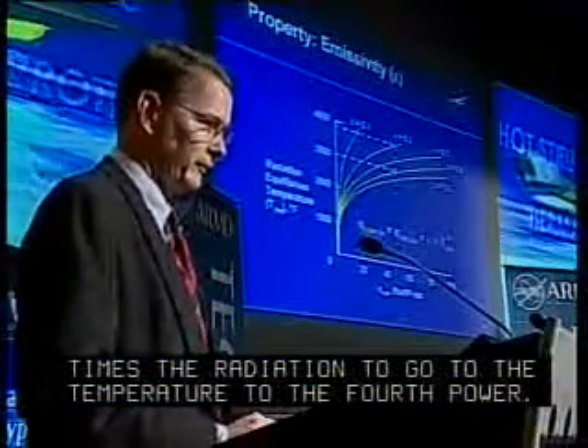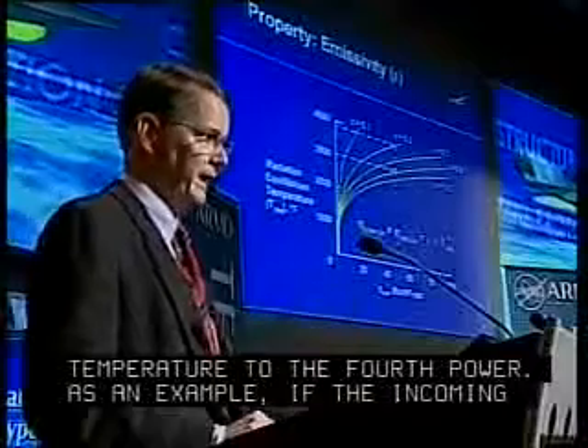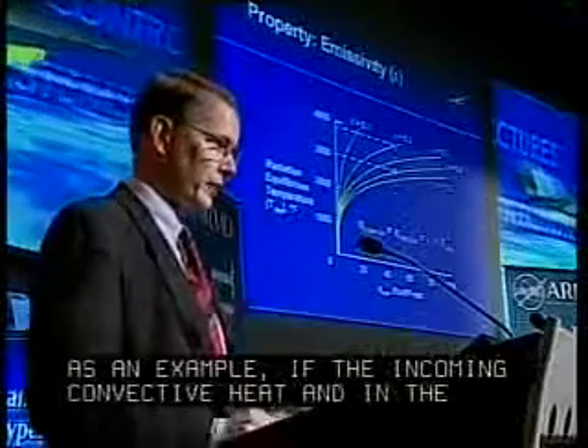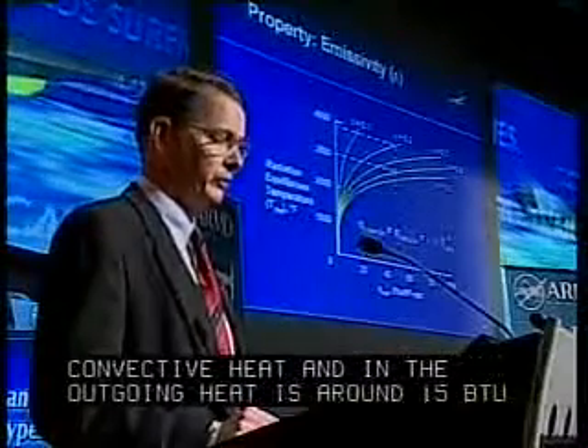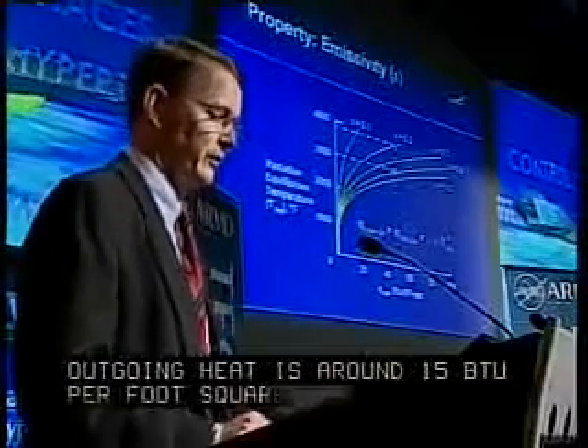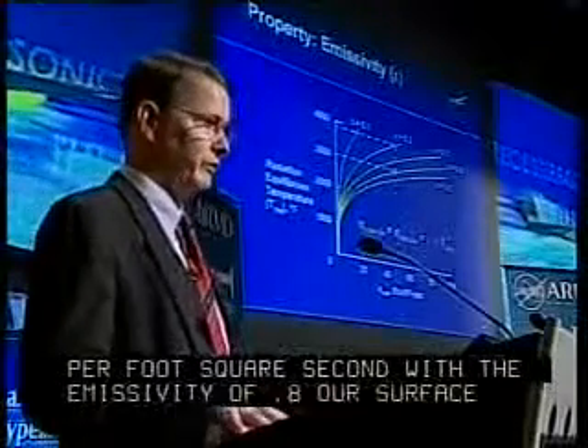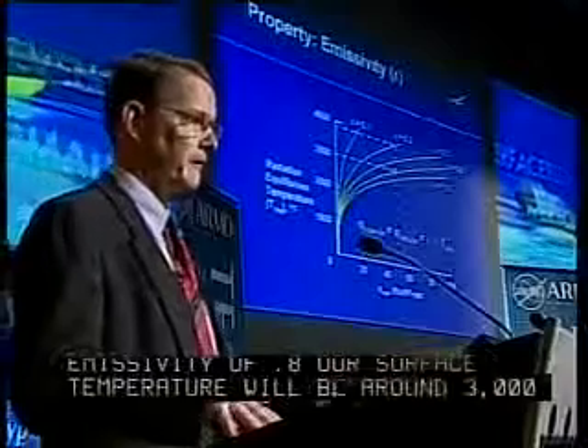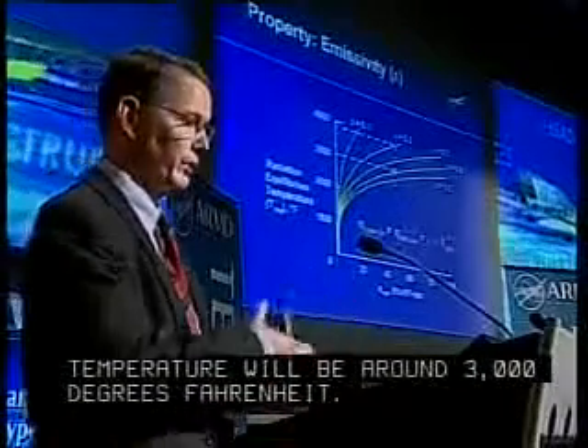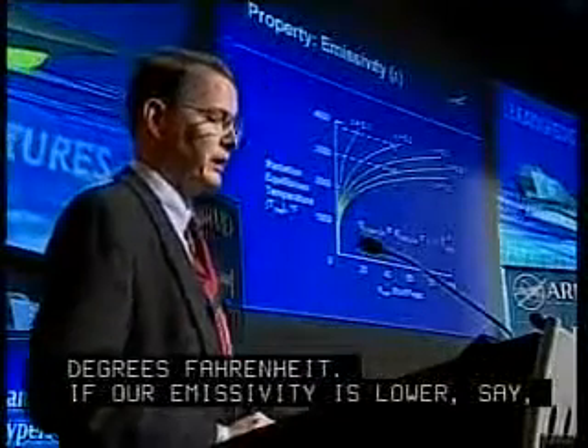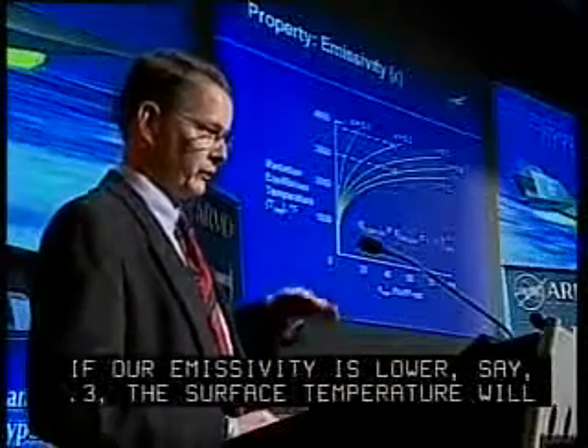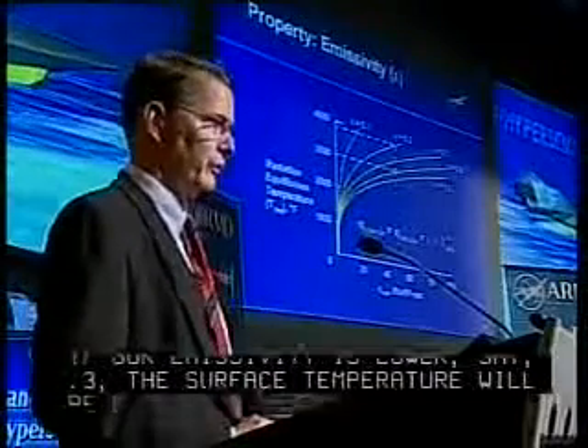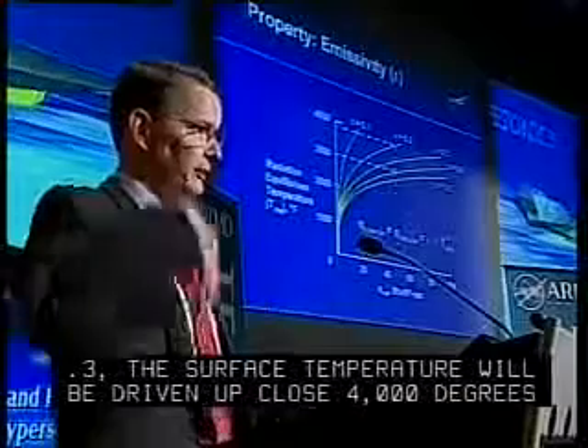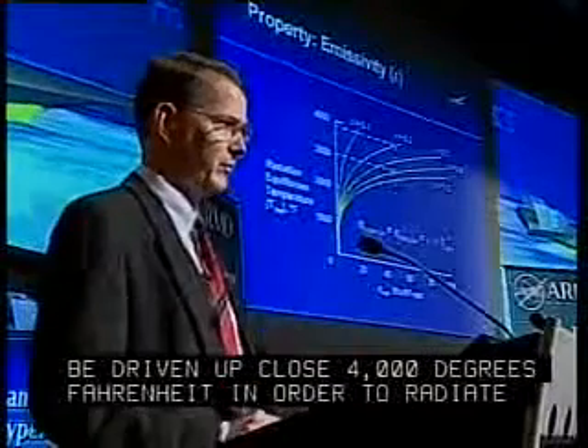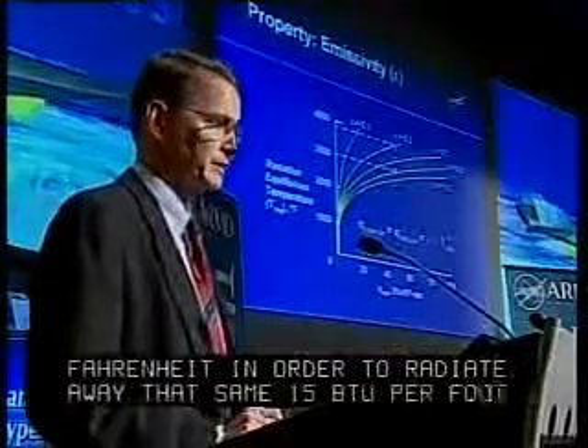As an example, if the incoming convective heat and then the outgoing heat is around 15 BTU per foot squared second, with an emissivity of 0.8, our surface temperature is going to be around 3,000 degrees Fahrenheit. Okay, if our emissivity is lower, say 0.3, the surface temperature will be driven up to close to 4,000 degrees Fahrenheit in order to radiate away that same 15 BTU per foot squared second. Next chart.